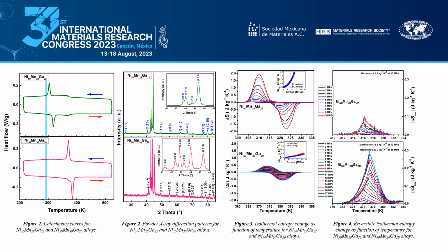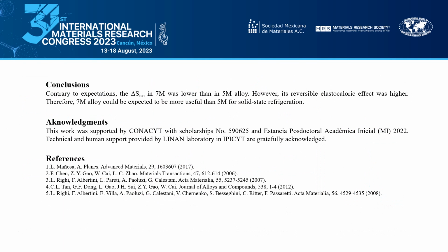These results are directly related to the thermal hysteresis of the alloys and the displacement of the transformation temperature as a function of the applied stress. The conclusion was: contrary to expectation, the isothermal entropy change in 7M was lower than in the 5M alloy. However, its reversible elastocaloric effect was higher. Therefore, the 7M alloy could be expected to be more useful than 5M for solid-state refrigeration.